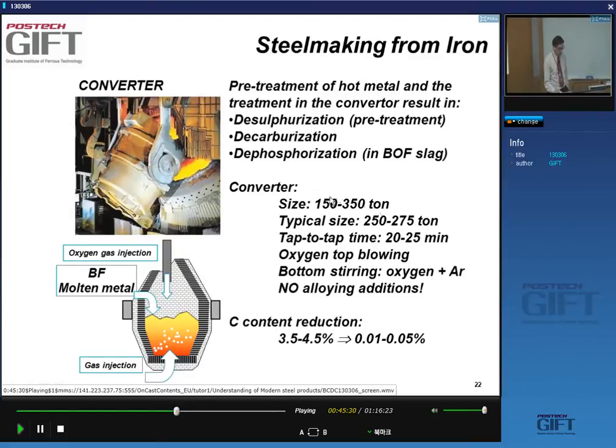These converters are very large, 150 to 350 tons, they range. This is the range that you find in the industry, but the typical sizes are 250, 275. That's a typical modern converter. The time it takes to produce this amount of steel is 20 to 25 minutes. So every 20 to 25 minutes a converter can produce about 250 tons of steel. You have oxygen top blowing. At the bottom you inject argon, sometimes mixed with oxygen.